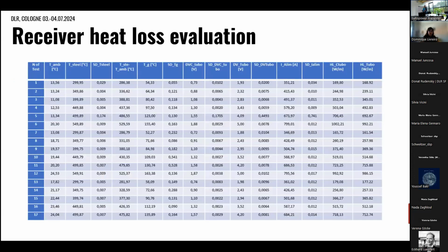Here I reported a summary of the results that we have obtained in one of our tests on one receiver. And also reported the standard deviation for the voltage, the heat loss, and also for the steel temperature. But we can see that the standard deviation is very, very small, in the order of 0.1%. So we can say that the measurements are very accurate. The system of measurement is very accurate.